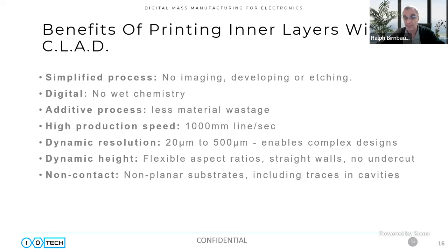Speeds are production, basically industry speeds. The resolution is okay for the majority of the PCB market, except for the extremely fine HDI. So 20 micron and above is good. Additional benefits are, as opposed to chemical etching, there's no undercut. So we build up the straight walls of the lines. And because it's non-contact, we can also use non-planar substrates up to a limit in thickness, of course, including going down into cavities and going up as well.